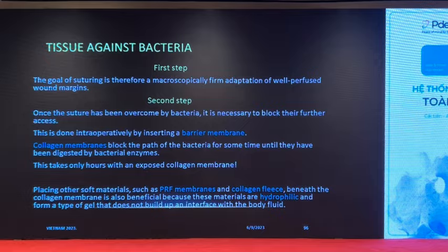Collagen membranes block the path of the bacteria for some time until they have been digested by bacterial enzymes, and this takes only hours if the membrane is visible or exposed to the oral environment.